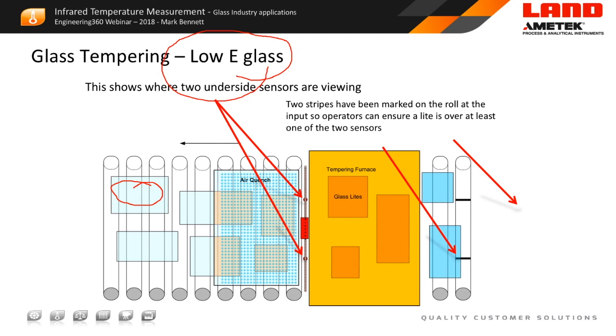And furthermore, this emissivity value here can vary from batch to batch as it is passed through the furnace with different processes. So what AMETEK Land have is a solution where we automatically compensate for the emissivity changes. We use single point thermometers to measure the underside of the glass, and we correct the emissivity on the fly in the scanner that's measuring the top surface, giving us an accurate and reliable repeatable temperature reading.